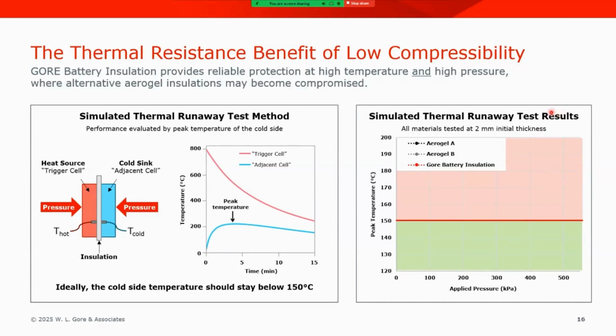So let's start with aerogel A. You see that initially, under modest compressive stress, we do maintain a fairly low peak temperature of about 135 degrees. But as soon as the compression is increased and the stress is increased, you see that very quickly we jump above 150, and in fact, at 500 kilopascal, we're up to almost 195 degrees C. So this would be a non-ideal condition.